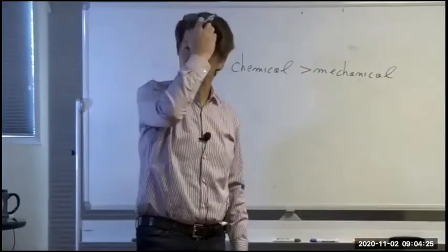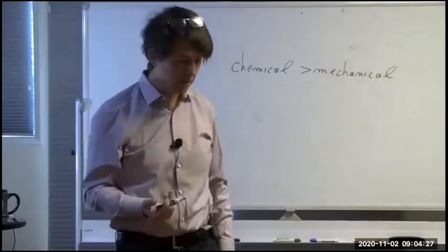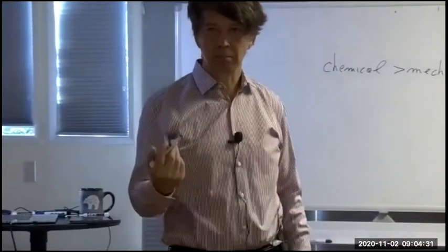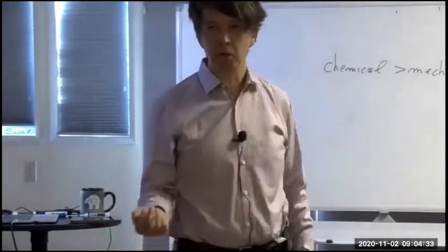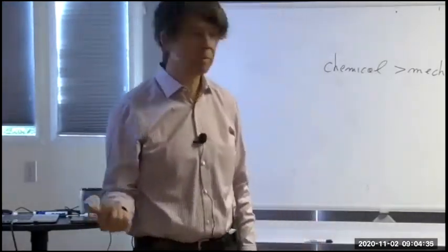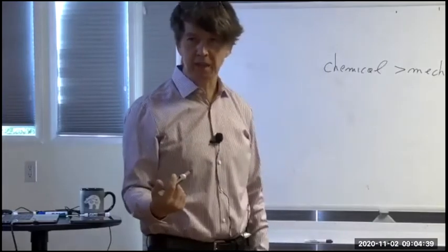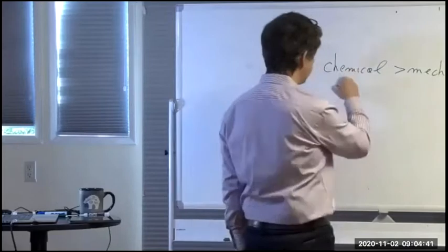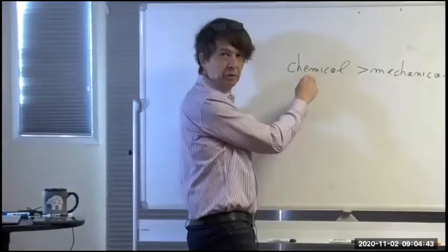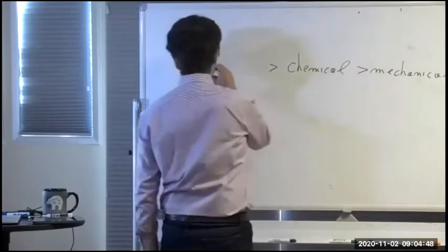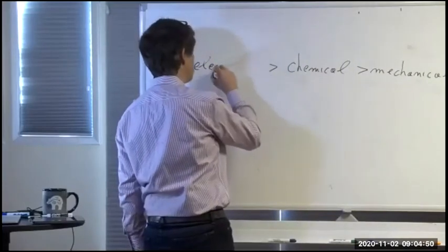We've shown that. PV terms are very small. Elastic terms like sigma times epsilon, within reasonable ranges of sigma and epsilon, are very small on the chemical scale. Remember that? We did examples of that. Here you're talking tens of kilojoules, often hundreds of kilojoules. Here you're talking a few joules. But what you now see is that electrical is even stronger.